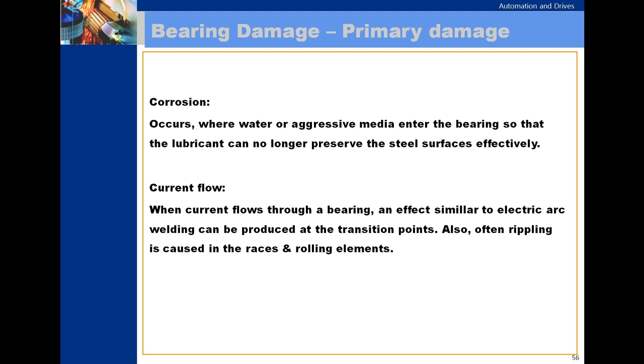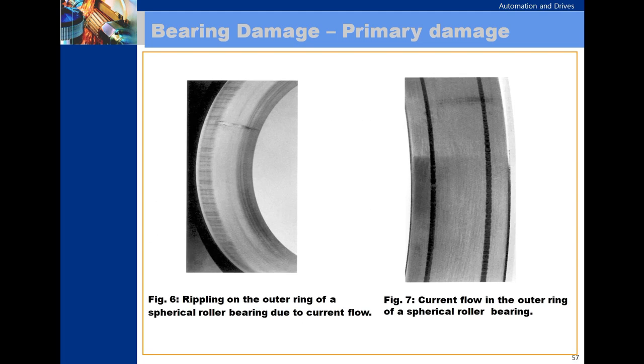Corrosion occurs where water or aggressive media enter the bearing, so that the lubricant can no longer preserve the steel surfaces effectively. Current flow: when current flows through a bearing, an effect similar to electric arc welding can be produced at the transition points. Also, rippling is often caused in the races and rolling elements.